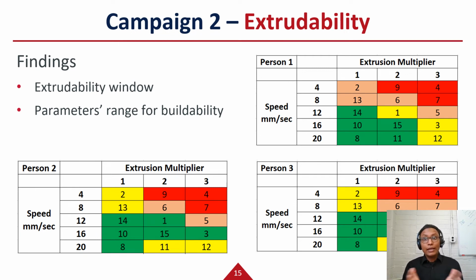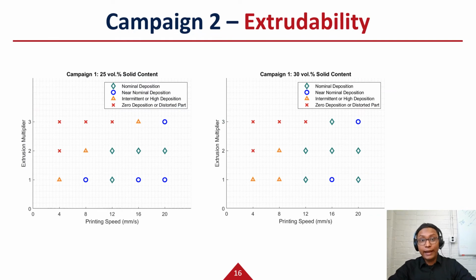For example, we can see that extrusion multiplier 3 is producing bad parts, which will eventually show bad shape stability in multilayered parts. Similarly, 4 and 8 mm per second speeds were not giving us nominal deposition as we wanted. We will exclude these settings in the next campaign. This slide and the next one graphically show the extrudability window for different solid contents.